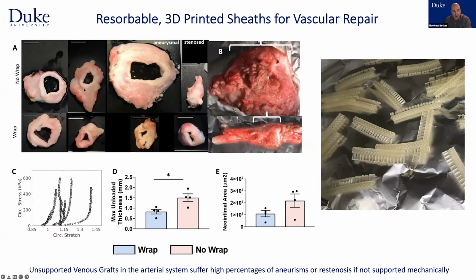But when you have an unwrapped system, you might get lucky. And if the arterial pressure is low, particularly in most females, then you'll have a gradual remodeling of that vein into a more arterial-like structure. But very often, if the pressure is high or at the graft points where you're suturing, you'll get an aneurysmal structure, or it will close and calcify and stenose. Whereas if you have this structure wrapped, so far it looks like we're getting very phenotypic remodeling from veins into artery. And I think that's potentially very exciting, both clinically and commercially.